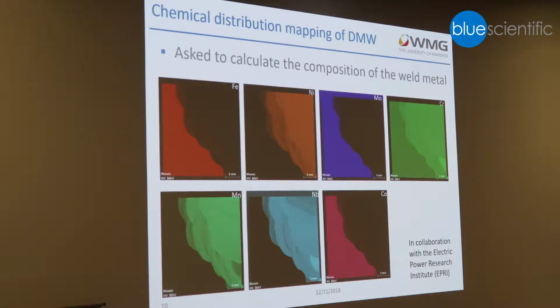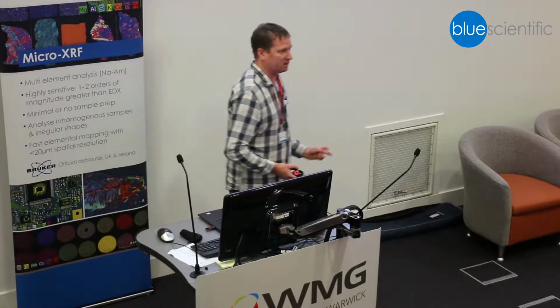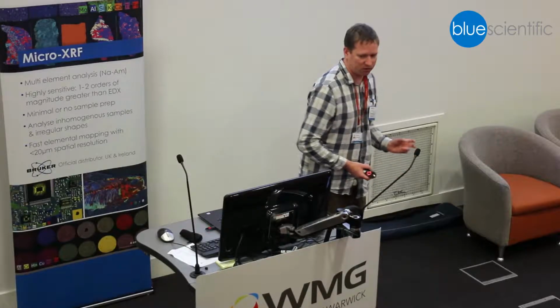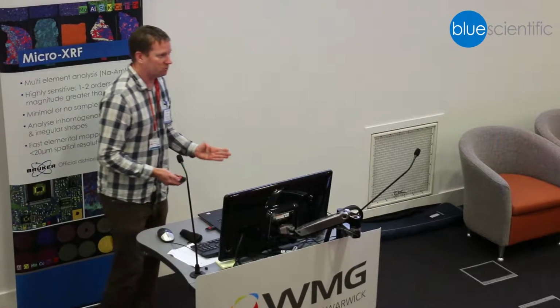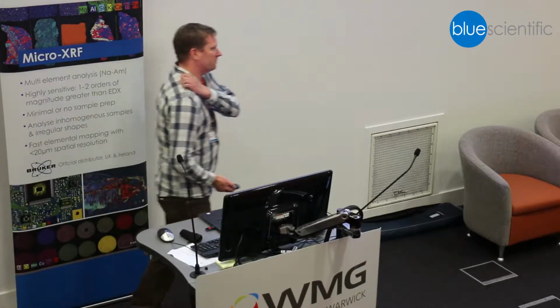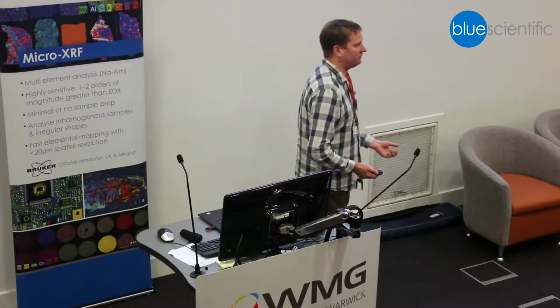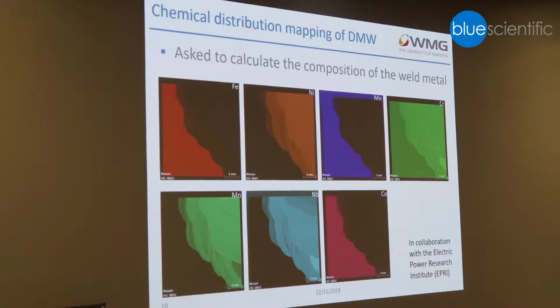The next example I'd like to show is some work that we did on a dissimilar metal weld, or DMW. We got these samples from the Electric Power Research Institute in America, and the question they asked me is, what's the composition of the weld metal? So what we would do if we didn't have Micro-XRF is we'd stick it in an SEM, and we would do chemical analysis in maybe 10 regions and take an average. But when you look at the length scales over which the chemical composition changes in this sample, that would not be an adequate solution, because you can see that all these different weld beads have different compositions.